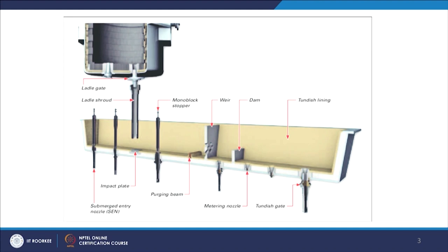One of the roles is to have proper fluid flow inside the Tundish to ensure many things, and among them the important thing is proper homogenization of the temperature inside the whole Tundish. For that you use these flow modifiers, because otherwise the metal will go towards the bottom, a bottom-directed flow. You may have stagnant regions in certain parts of the Tundish, and that forms dead volume. That effectively reduces the effective volume of the Tundish, and will also lead to cold regions, which is further detrimental as far as the productivity of the Tundish is concerned.